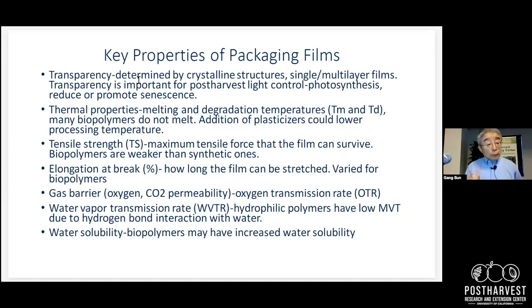But if it becomes amorphous, there's also an issue related to the tensile properties, so the tensile strength and also the elongation. Amorphous is less stable, less strong than crystal. Also, thermal properties are determined by the polymer structure itself. All our natural polymers are good in general, but most of them do not melt. So if you want to process and utilize them to make them into films, you have to find a solvent. Otherwise, you have to chemically modify them to make them what we call thermoplastic-like. So meltable is called a thermoplastic.